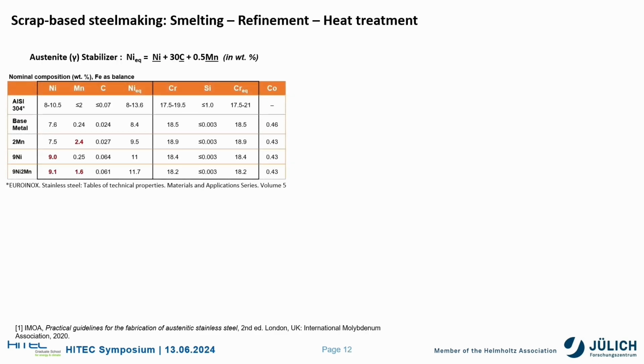One thing we have forgotten: in the production of austenitic steels like 304 steel, particular attention has to be given to this nickel equivalent value to ensure that austenite remains retained at room temperature. And this is calculated based on the weight fractions of certain austenite-stabilizing alloying elements multiplied by certain weight factors. For the 304 steel, its value is within the range of 8 to 14. For the base metal, it's at 8.4, which is at the lower end, and this might be the reason why austenite was metastable.